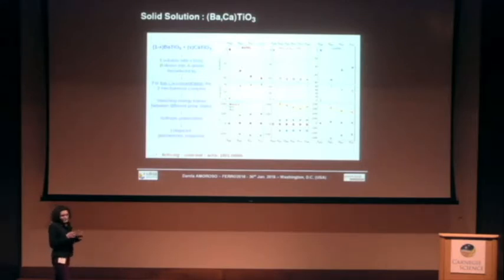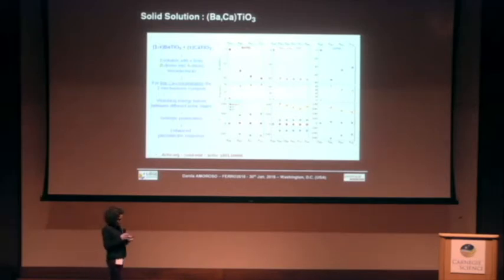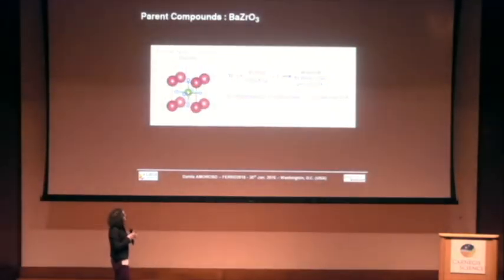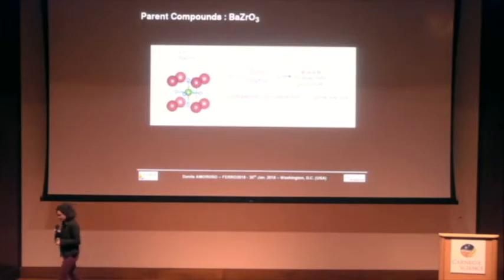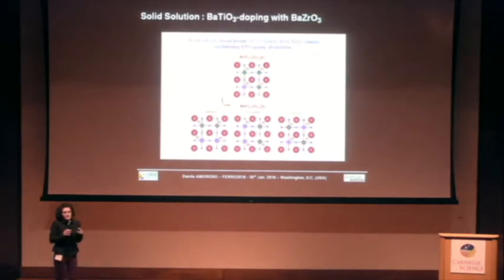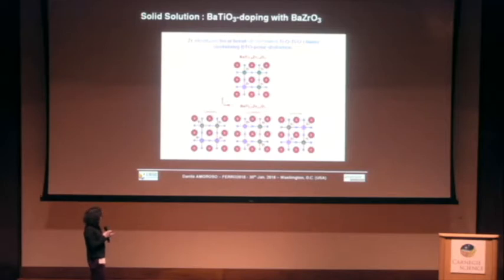But now we need also to care about the doping of the B site. And so we need to deal with barium zirconate. Barium zirconate presents a third different behavior because it likes to be cubic, in fact, and accordingly the interaction between zirconium and the oxygen atoms is a stable one. And in fact, zirconium is polar inactive. But so actually we can already imagine what is the effect of this doping. What happens when we substitute one atom of titanium with one atom of zirconium?